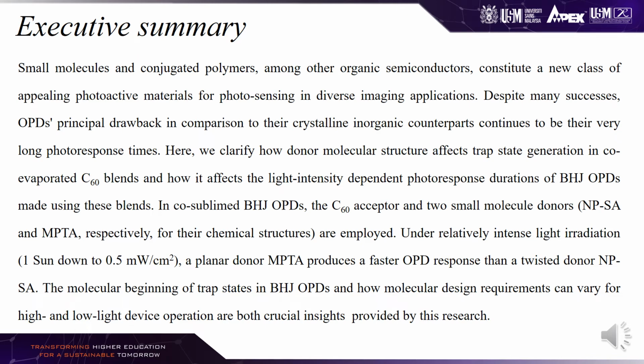In co-sublimed bulk heterojunction organic photodetectors, the carbon-60 acceptor and two small molecule donors, NPSA and MPTA respectively for their chemical structures, are employed. Under relatively intense light irradiation, which is 1 sun to 0.5 milliwatt per centimeter squared, a planar donor MPTA produces a faster OPD response than a twisted donor NPSA. The molecular origin of trap states in bulk heterojunction organic photodetectors and how molecular design requirements can vary for high and low light device operation are both crucial insights provided by this research.